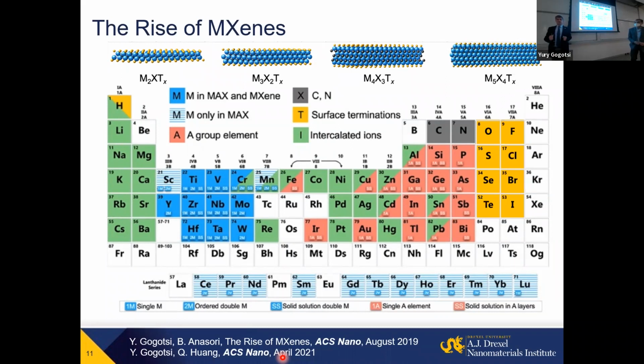Another big issue, which I mentioned very briefly, was stability. MXenes can hydrolyze. They're carbides, nitrides. They can react with water. They can react with oxygen. It appeared that stoichiometry, the transition metal to carbon stoichiometry, is really the key. Point defects on the surface, over-etching is another question here, and flake size.